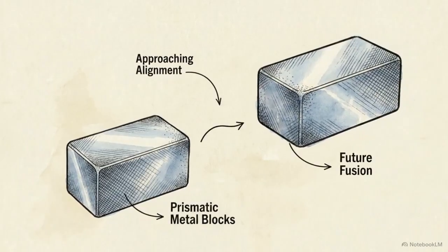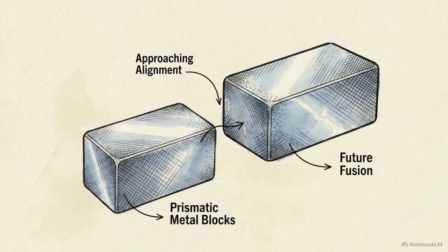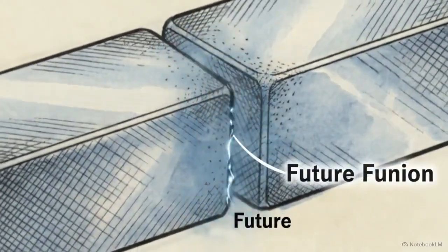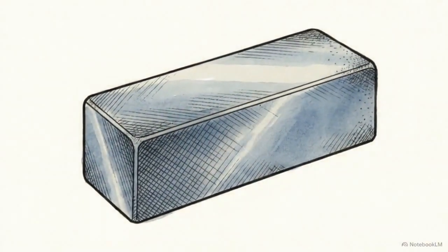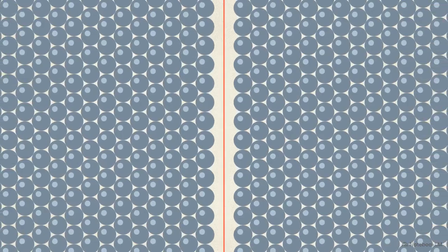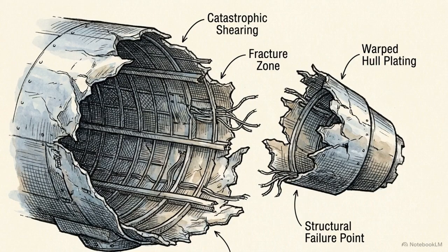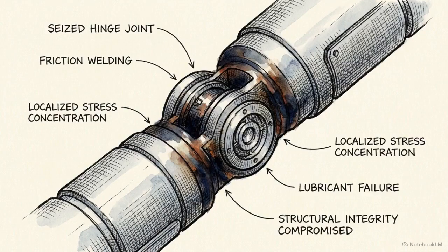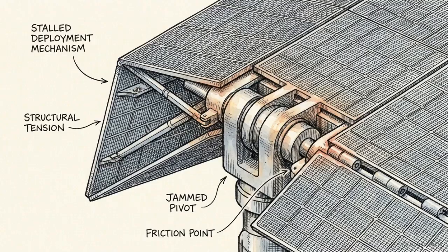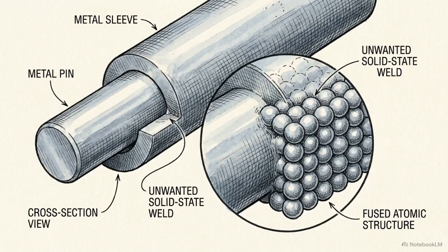But the vacuum of space provides unique physical conditions. When two pieces of clean, oxide-free metal make contact in a vacuum, they undergo cold welding, the spontaneous solid-state bonding of their atomic structures without any applied heat. The two pieces become indistinguishable from a single bulk crystal. For decades, aerospace engineering has treated this phenomenon exclusively as a catastrophic failure mode. Unlubricated moving joints, hold-down points, and deployment mechanisms have seized in orbit when polished surfaces inadvertently fused under load and